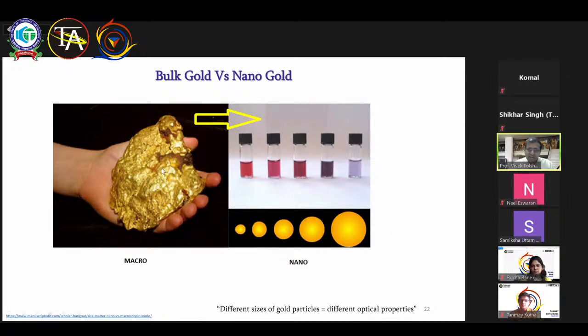When you convert this bulk gold into small nanoparticles of gold, you see now the nano golds start showing different colors. What happens at the nanoscale is the electron cloud that was reflecting the light now becomes so mobile that it doesn't reflect the light, but it starts oscillating by interacting with the electric field. And at one particular wavelength, it absorbs that light, those particular photons, and that gives you different colors, right? So that's called the surface plasmon resonance. And you can see now a dramatic change in the properties of the material, in this case the optical properties of the material, when you go to the nanoscale.